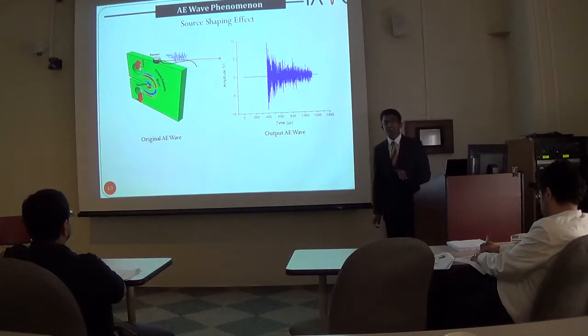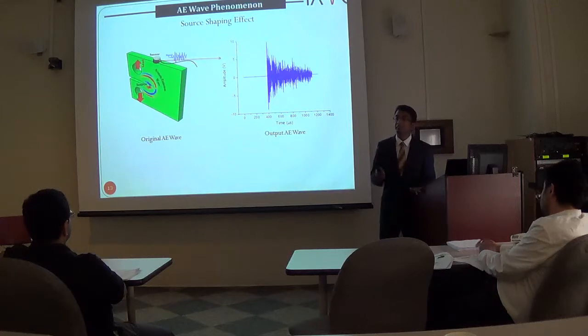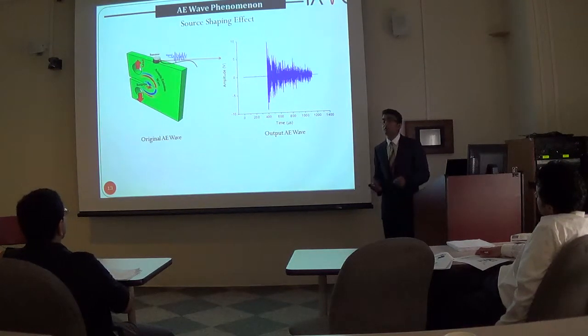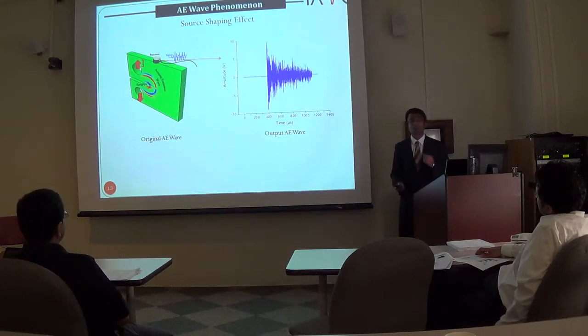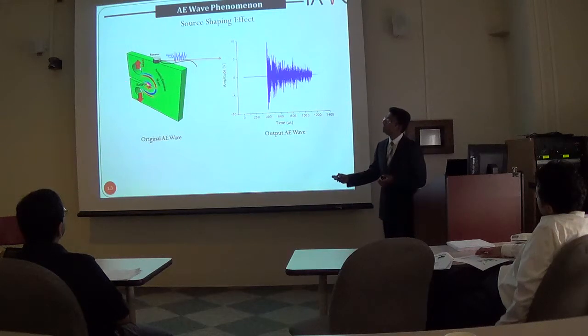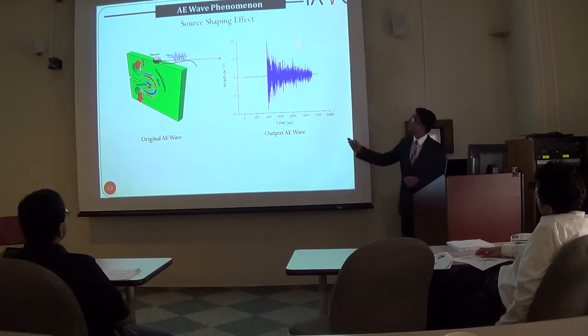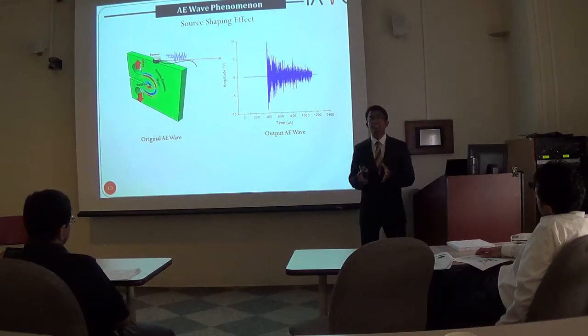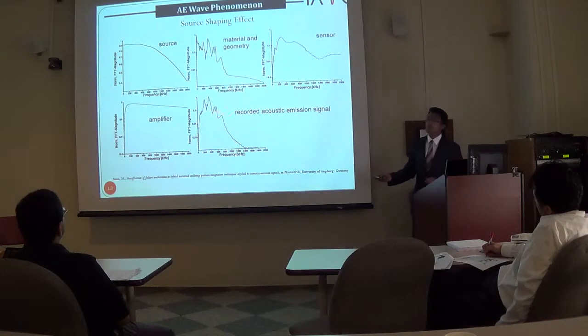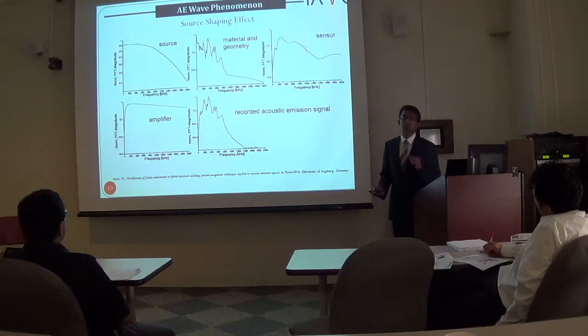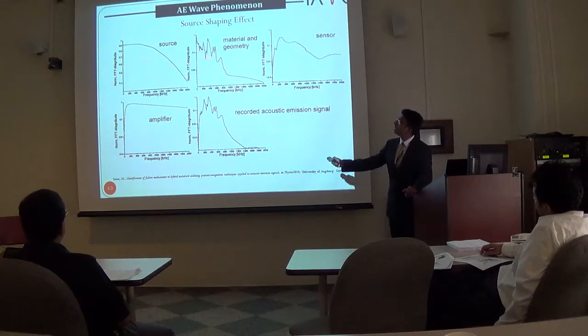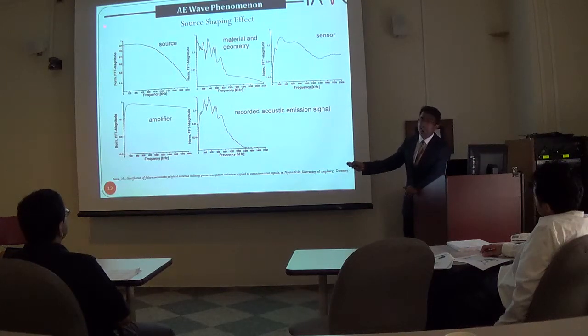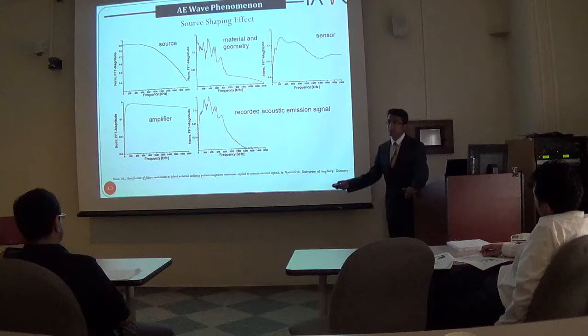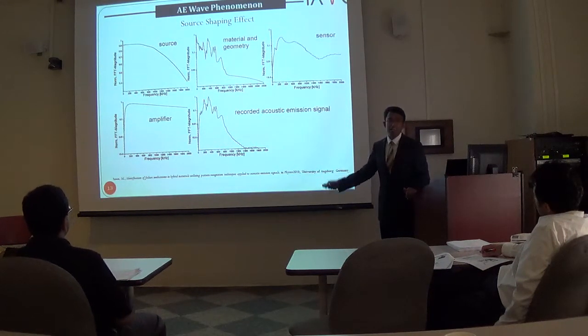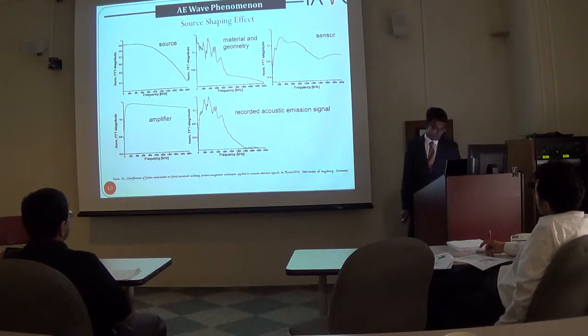Now, the other important factor that needs to be understood with acoustic emission testing is the actual AE wave phenomenon that happens in the material. To ensure the reliability of damage detection using acoustic emission, it is important to understand how the waves are produced and propagated in the material. For instance, the original AE waveform that is produced by the material due to a damage and the final AE waveform that is picked up by the sensor do not share a linear relationship. In fact, the final AE waveform picked up by the sensors is a convoluted transfer function of several different mechanisms. For instance, the initial source AE waveform has a frequency characteristic as the one shown here, but as it propagates in the material and the geometry, it is severely colored and affected, which is further affected by the utilized sensor and the instrumentation in the test. Thus, the finally observed AE signal is a convoluted function of all these different mechanisms.